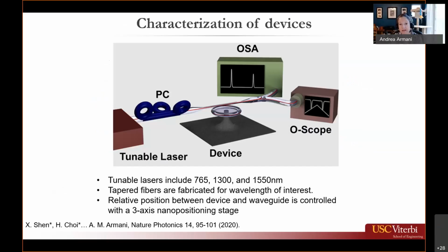To characterize the devices, we used a tunable laser. We actually used 765, 1300, and 1550 nanometer lasers. We then ran our laser through a polarization controller so that we could look for that polarization dependence. We coupled that into our device using a tapered optical fiber waveguide, and then the output signal was split between an oscilloscope so that we could measure the Q factor, and an OSA, or optical spectrum analyzer, so that we could measure the output spectrum.